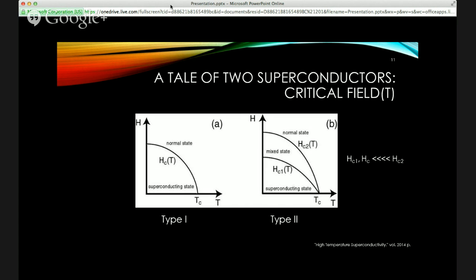So now I mentioned the type 1 and type 2 as a temperature distinction, but this is more on the critical field side. So for type 1 superconductors, it's either in a superconducting state or it's in a normal state. There is no in-between. However, type 2 superconductors have three states. They have a superconducting state where you have the HC1 as the boundary for that. And then in between HC1 and HC2, you have a mixed state. And at this point, you're actually allowing some of the magnetic field into the actual superconductor. However, it's still able to function and operate as a superconductor with these magnetic flux lines present in the superconductor. And then outside of HC2, when the field is higher, it's in a normal state.